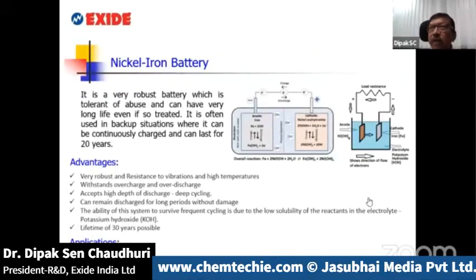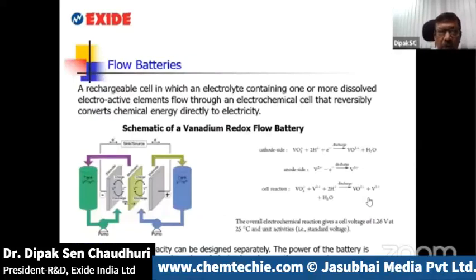Nickel cadmium is a battery which all of you are familiar with, but people have moved across from nickel cadmium because of environmental and other issues. In the nickel family, perhaps the most promising candidate in our energy storage applications is nickel iron. This is again a very old technology which was developed 50, 60 years back. And this is a product which is extremely robust, which can handle a lot of abuse. This is very critical in terms of both overcharge and particularly over discharge. But it can deliver an extremely long cycle life. So this has also been there, but it has been more plagued with manufacturing issues. So it has never become very popular.